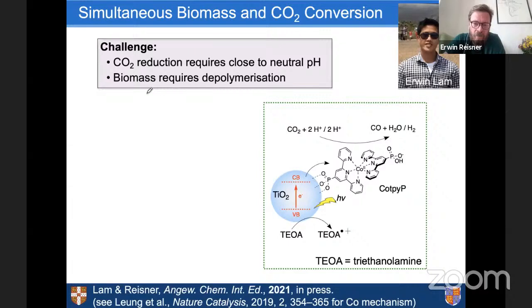And in fact, there are not that many systems. And the one we settled for looks like a trivial system, but it's not. So we use titanium dioxide as a light absorber. The limitation here, again, is that it's a UV light absorber, but here it's just about showing the chemistry. But the tricky thing is reducing CO2 with titanium is very difficult because the driving force you have is only about 200 millivolts, and you really need a very efficient catalyst.